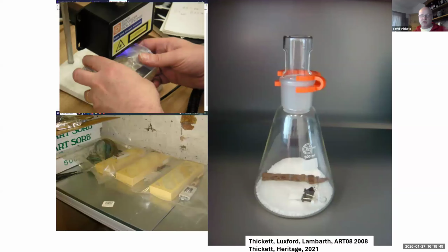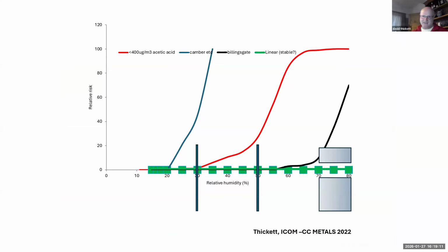And as I say, we've been working on this for about 25 years, and we found a way that we can measure the deterioration rate by enclosing the object with some silica gel to control the relative humidity and just measuring the oxygen concentration. And if it's deteriorating, it's unstable, the oxygen concentration will drop. We can do it for small objects with glassware or larger objects with Escal bags. And the testing takes about 2 weeks. And having tested now well over 3,000 objects with this, and other groups are working as well, we've got quite a good methodology of doing it.